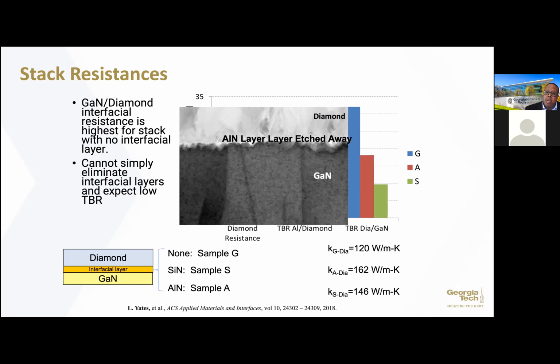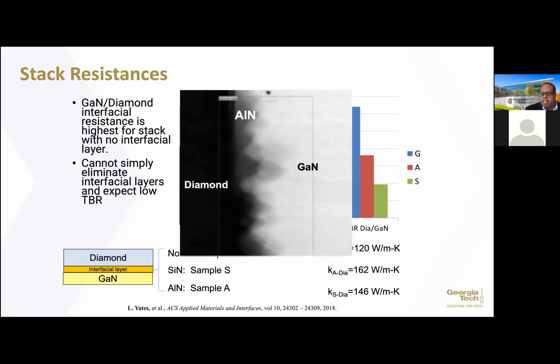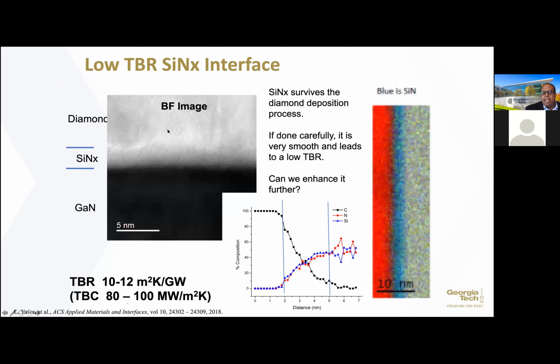I will say Martin Kuball's group in Bristol has worked on this a bit more, and they've been able to make this better. But this is at the time when we published this, this is where we were. And then you get to silicon nitride, and it has the lowest thermal resistance. So what is happening here? What we ended up seeing is that this 5 nanometer thick layer of silicon nitride, you can barely see it, has some etching, but it only etches down to about 3 nanometers in thickness. So you still have that silicon nitride layer that remains.